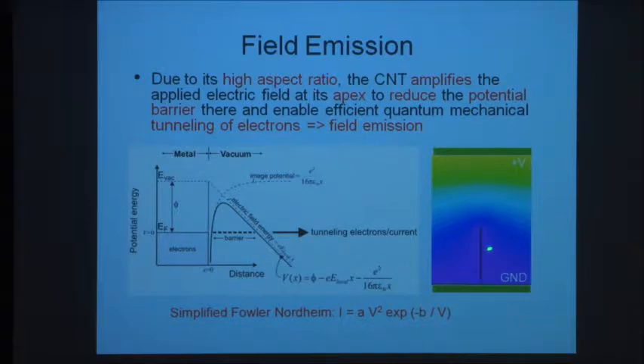However, if you have something shaped like this, which you may note a carbon nanotube looks a bit like, you apply a bias, the field focuses on the top of the nanotube, and you get an enhanced field. So at any given field up here, you get an enhanced effective field on here, which leads to a much higher field and much more efficient tunneling of the electrons. So due to its high aspect ratio, the CNT amplifies the applied electric field to reduce the potential barrier and enable efficient quantum mechanical tunneling of electrons. That's field emission: application of a bias to drag electrons out of a material.